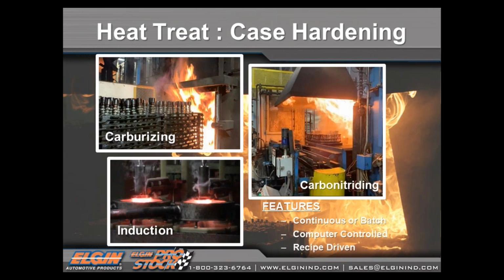to sustain your wear. You say, well, why does the core have to be soft or ductile? It's because engines are built to run longer, right? If you have a solid heat-treated part that is hardened all the way through, it will be very strong for very short periods of time. Everybody wants an engine to last today, and in the diesel industry, we're looking at upwards of 10,000 hours of service. So you want a part that can go through multiple cycles of flexing and stressing and not fail in fatigue. You can generate case hardened parts in a number of different ways.